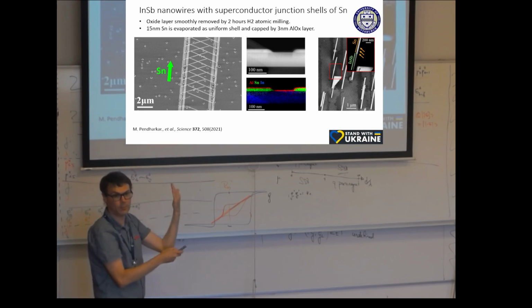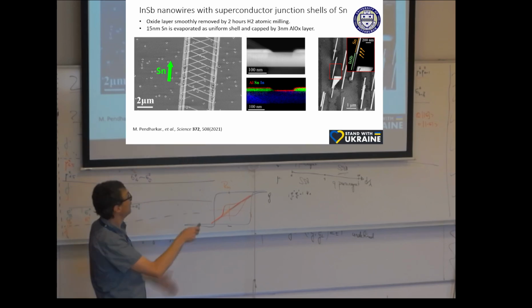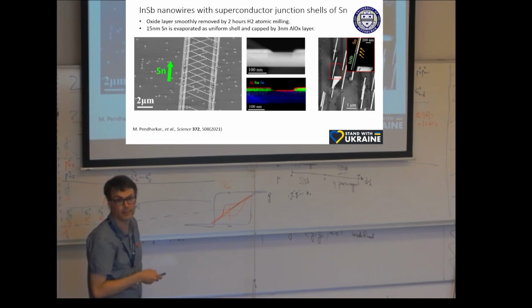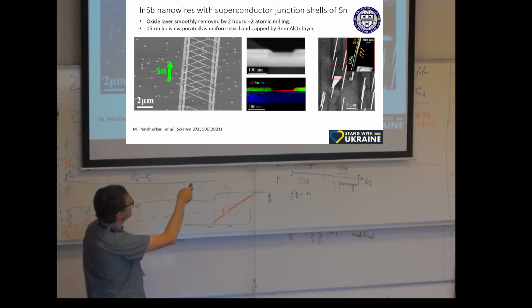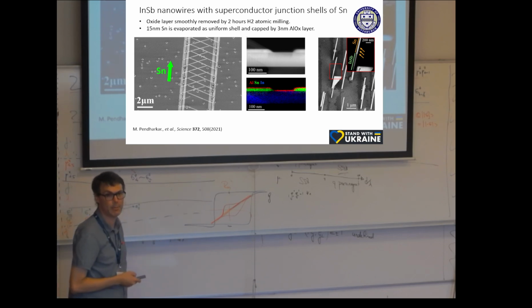And then the front wire is fully coated. The back wire, there is a shadow. This shadow is created by the front wire. Shadow here, right? So we make a junction: tin, indium antimonide, tin. That's the Josephson junction, like this. This is about 120 nanometers, which is the diameter of the wire.